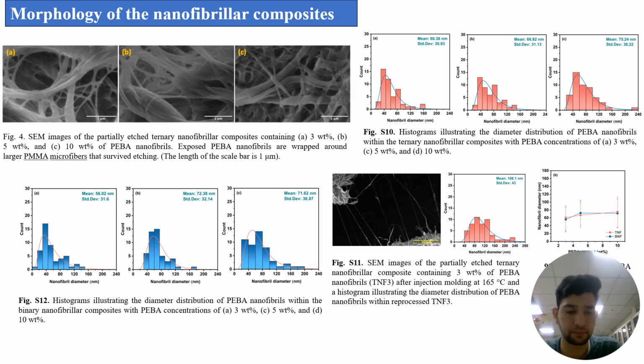In the spun bond processing, the extrudate undergoes stretching, as I mentioned in the experimental portion. Stretching and rapid cooling by high velocity cold air cause the dispersed droplets to deform, elongate, and coalesce into an integral fiber morphology of high aspect ratio fibrils. The extent of the droplet-fibril transition and the final nanofibril diameter are influenced by factors such as viscosity ratio, fibril-fiber coalescence, temperature profile, screw speed, feed rate, spinneret hole diameter, and air velocity.